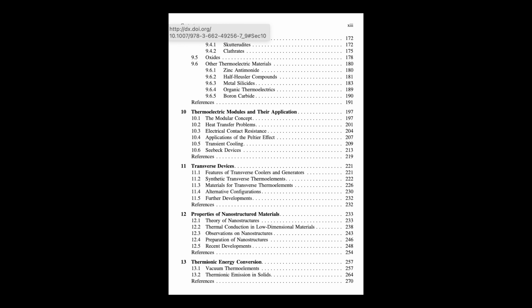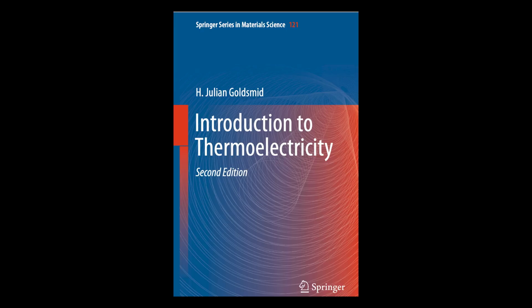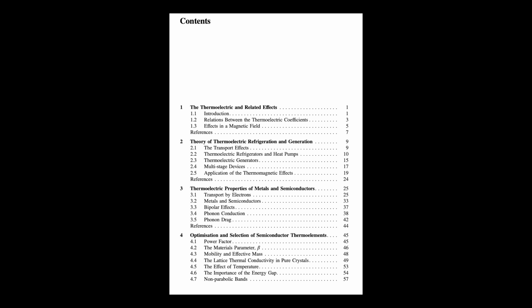Which leads nicely to the phonon glass electron crystal, or PGEC, concept. Sounds like the dream material. It really is. PGEC is the holy grail. The idea is a material that conducts heat like a glass, very poorly, because glass is disordered and scatters phonons like crazy. But at the same time, it conducts electricity like a crystal, very well, because electrons need an ordered path. Achieving both is the ultimate goal. People try all sorts of tricks. Complex structures with rattler atoms shaking inside cages to scatter phonons, or engineering lots of nanoscale interfaces. Super low heat flow, super high electron flow.